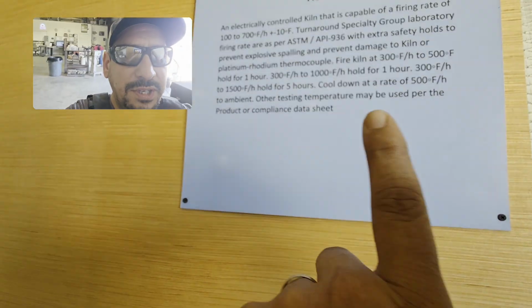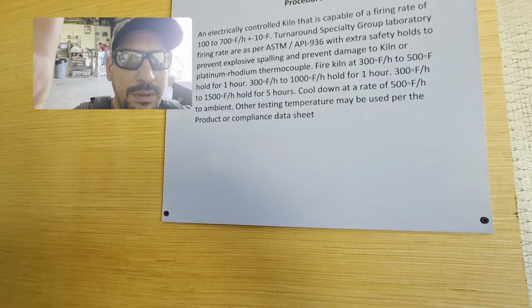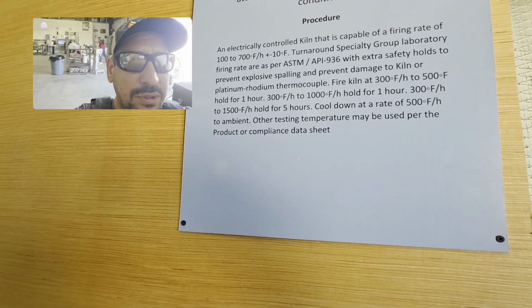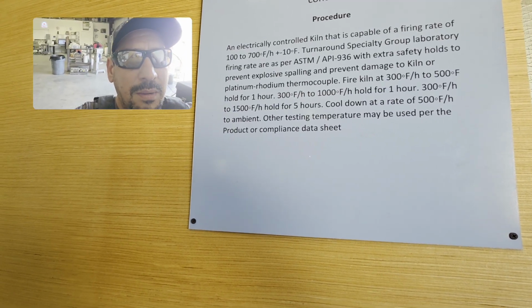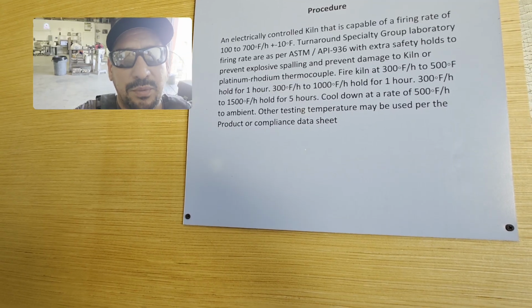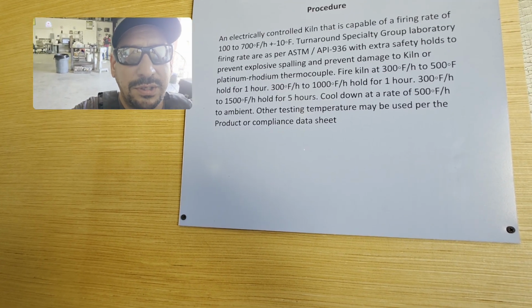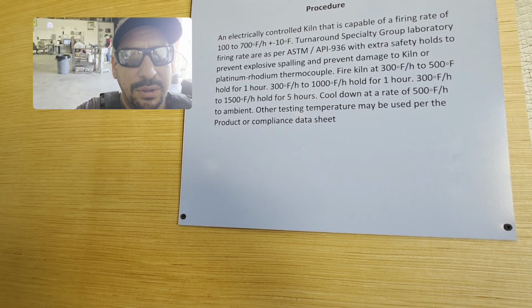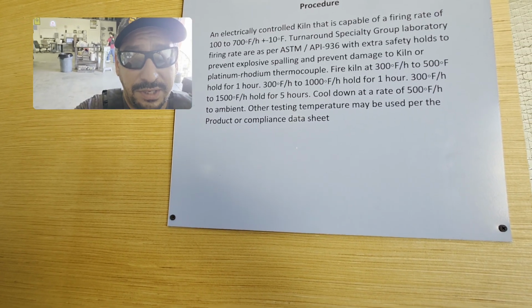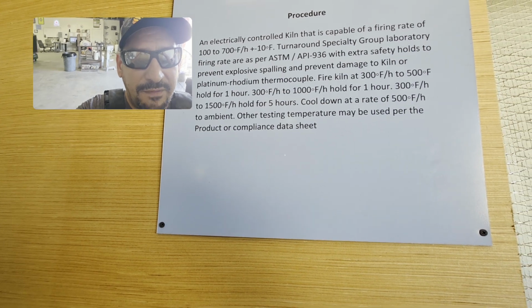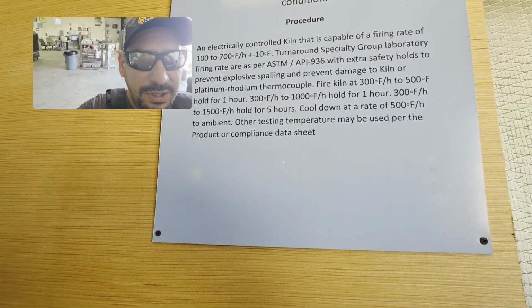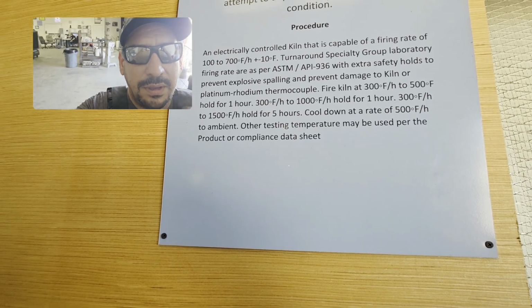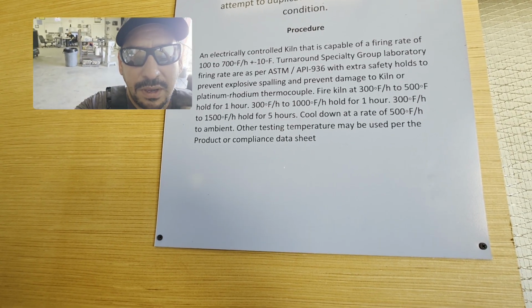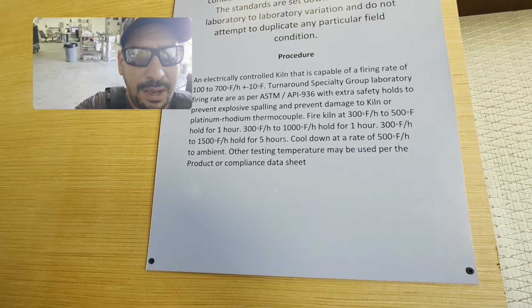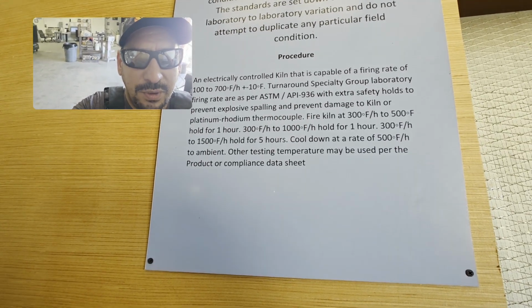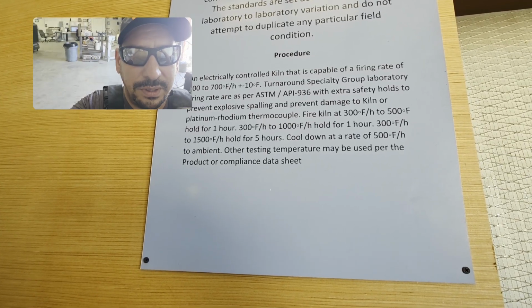All this other stuff up here, that's just something that we do here at the shop, in the lab, to ensure that we don't have any spalling. But all this is rolled up into: it's going to go 300 degrees an hour until it hits 1500 degrees, and then we're going to hold there for 5 hours. That's a test question. The other test question they have for this is going to be the cool down rate. And as you can see right here, it's 500 degrees an hour to ambient. That's the standard ASTM API. But again, we just do extra here. So all that other stuff is just what we do here.